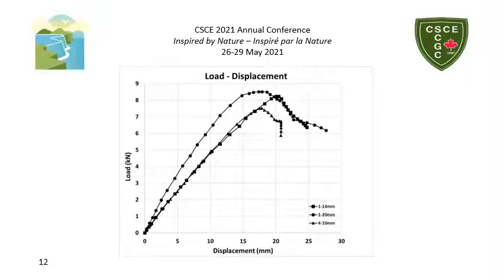Here are the three curves for the different rebar configurations combined into one graph. The load deformation data shows that the capacity depends mainly on the compression strength of the concrete, which makes BFRP rebar suitable for this application within the scope of this project. Despite the lower elastic modulus of BFRP rebar, the deformability for these specimens was within acceptable values.